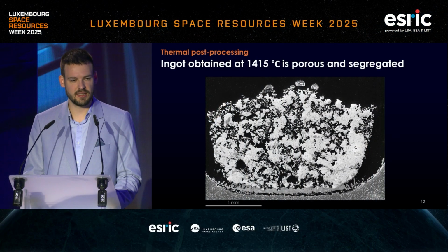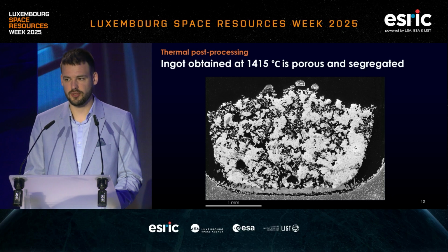This is what it looks like under SEM. A few interesting features we can see there. First of all, we can see it's still quite porous, although it has partially molten in some places. And we can also see a vertical segregation. So we see a separate phase collecting at the bottom of the crucible there.